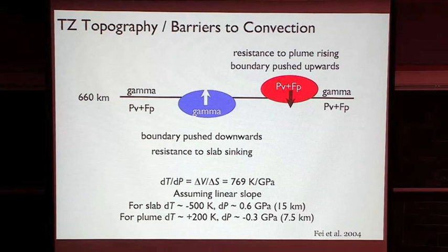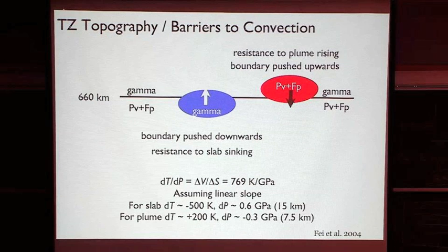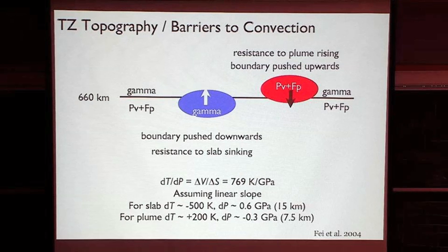Once you get to the perovskite phase, your technique, you know, David Rubie showed multi-anvil to diamond anvil cell. So this multi-anvil can just barely reach the perovskite phase. And most of these studies are multi-anvil studies where you have larger sample volume. Your measurements are more reliable. And if you want to study the curvature of the slope, then you need to convert it into diamond anvil cell. There are some measurements, but very controversial, very uncertain.